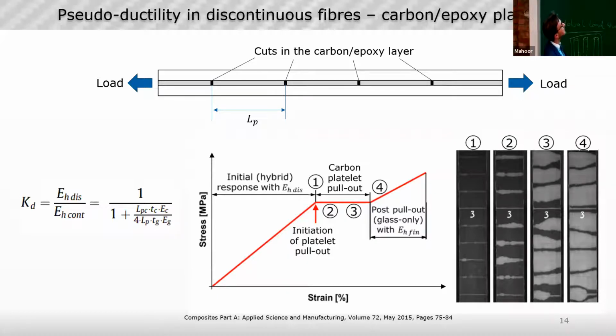Anyway, the problem with this, exactly, I was looking for this formula, sorry, is that we cannot create cuts as much as we want. And of course, the denser the presence of the cuts, the better the pseudo-ductile behavior. But of course, we reduce the initial stiffness of the material because we reduce the contribution of the carbon to the initial stiffness of the hybrid material. So we need to find a trade-off between the level of pseudo-ductility we want to achieve and the initial stiffness as well.